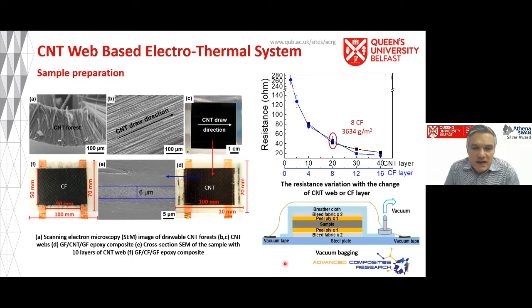Now, if I take one particular set of data points, we've got 8 plies of carbon fiber, the weight there is, as you can see there, 3,634 grams per meter squared, right? So comparatively heavy when you compare this to 20 CNTs, where you've only got 0.38 grams per meter squared, right? So you're going from kilograms to a fraction of a gram. So from a weight perspective, these things weigh next to nothing. And the way that we tested these carbon nanotubes, and indeed even with the carbon fiber as heating elements, is to put them between 2 glass fiber plies.